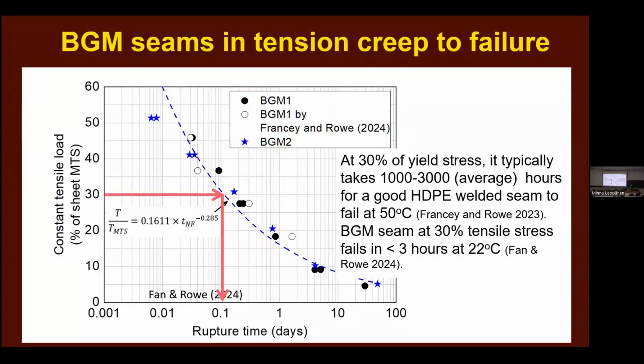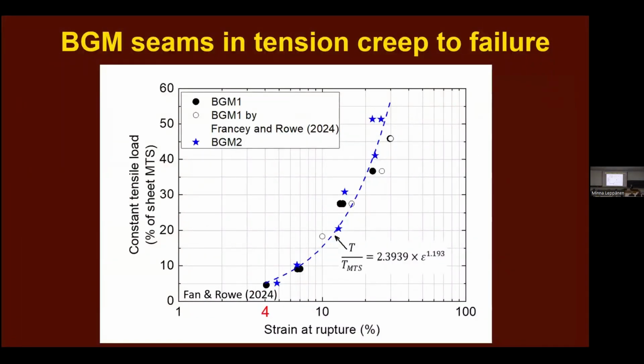Now, in comparison, if I take a HDPE weld it'll take 1000 to 3000 hours at 50 degrees Celsius before it fails at 30% of the yield stress, compared to less than 3 hours at 22 degrees for the BGM. Neither of them like stress, let's face it, but that BGM hates it even more than the HDPE. If we drop to 10%, we're looking at 128 hours. And what is the strain at rupture? Well, you can see that at 30%, it was about, let's say, 18% strain. At 10%, it was about 6% strain. HDPE, we test for stress cracking at 6% strain.